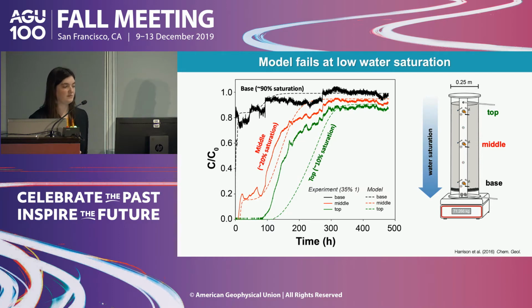Similarly, in the middle of our column, about 70% saturation, shown in red, pretty good agreement. But in the upper dry regions of our column, shown in green, we start to observe the biggest mismatch between our experiment and our model. Namely, our model is over-predicting the amount of reaction that has occurred.